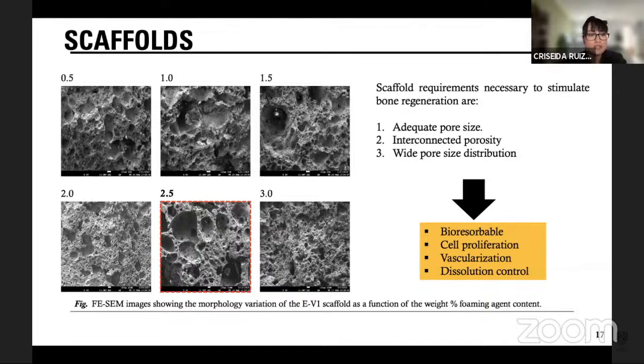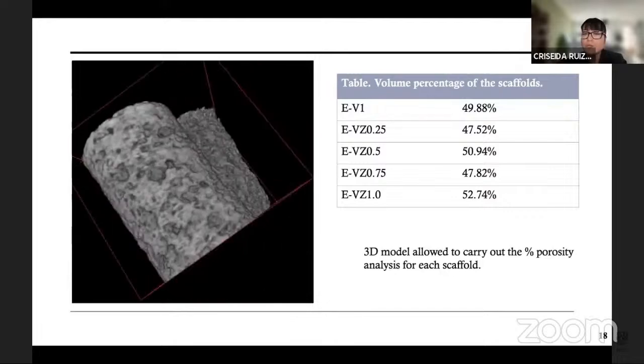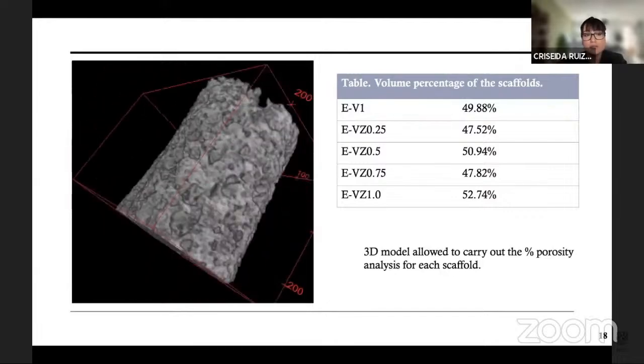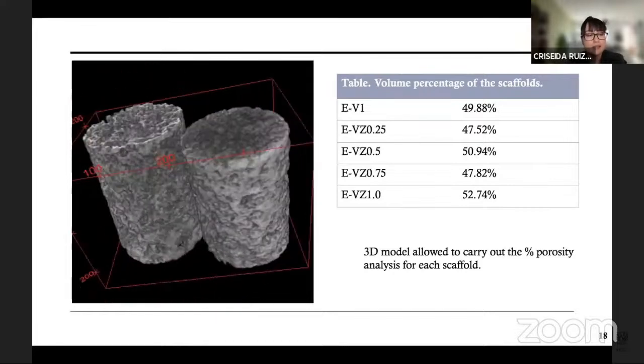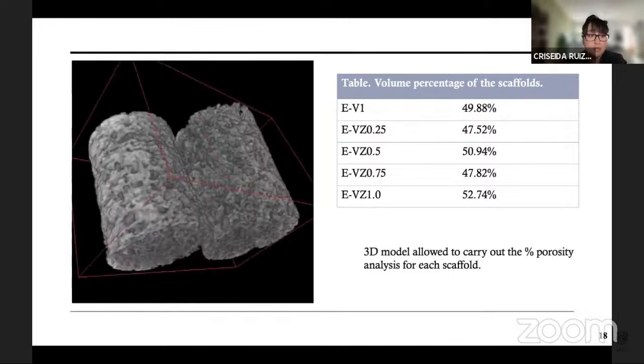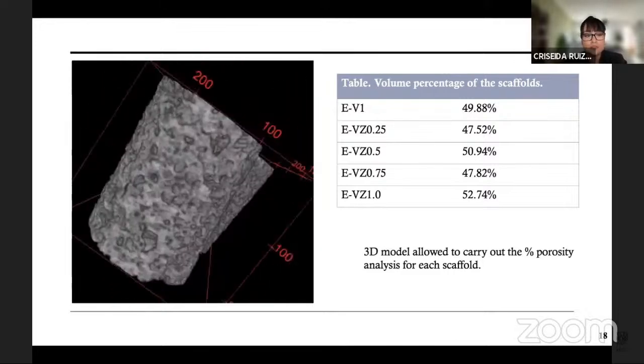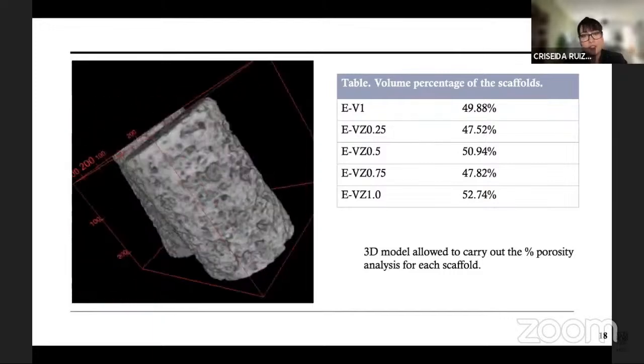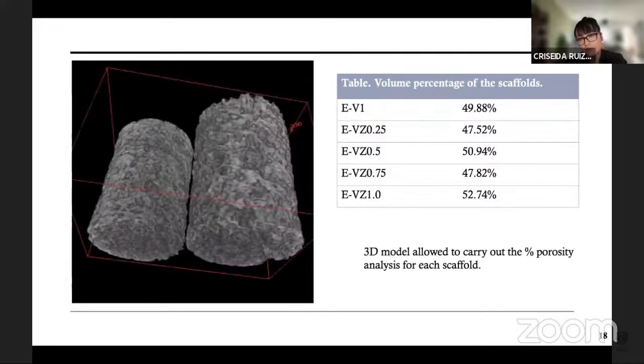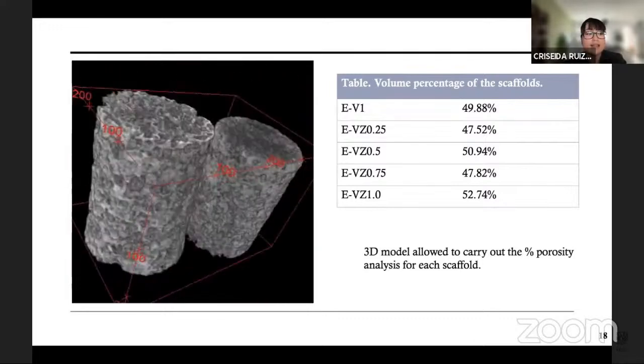So bone regeneration could occur in long bones, such as tibia, femur, or fibula. They had a wide pore size distribution and interconnected porosity. This aspect allowed resorbability, cell proliferation, vascularization, and a better control of the scaffold dissolution to be carried out. For the porosity analysis, two thick cuts were made using X-ray microtomography of the scaffolds, and then a 3D model reconstruction was made, as you can see in this video, which allowed us to obtain the percent of the porosity, varying from 49 to 52%. The range of the porosity is a consequence of the wide pore size distribution.